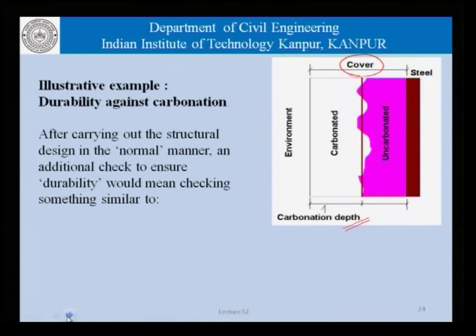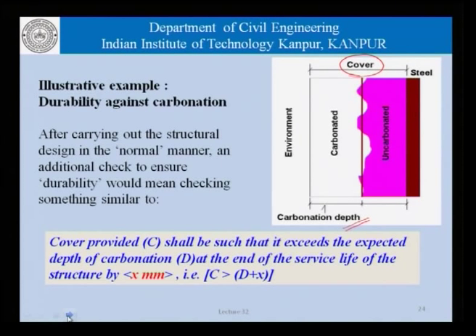In this case, after carrying out the structural design in the normal or the usual manner, an additional check to ensure durability would mean checking something similar to: the cover provided C, which is this value here, shall be such that it exceeds the expected depth of carbonation, which is d here, at the end of the service life of the structure by x millimeters, and this is the value x. So, we are saying that C should be greater than or equal to d plus x.